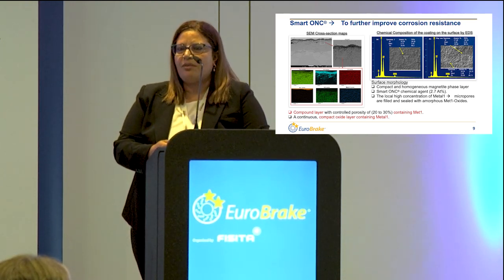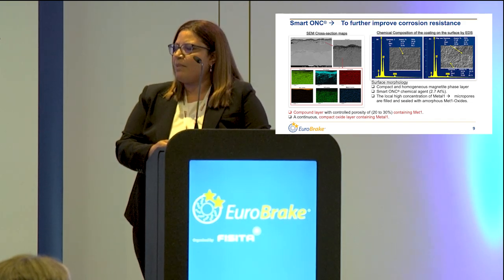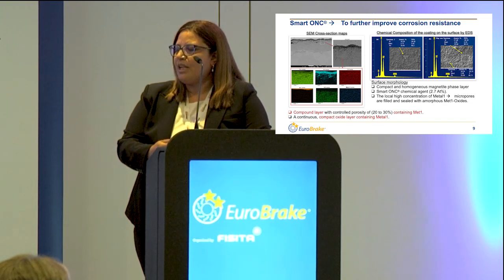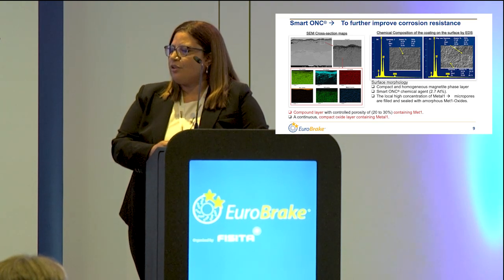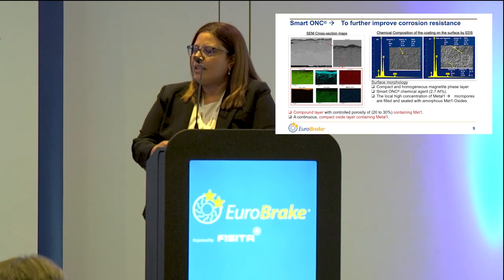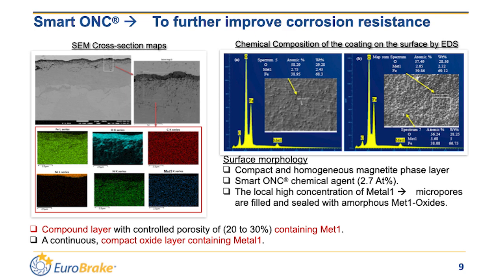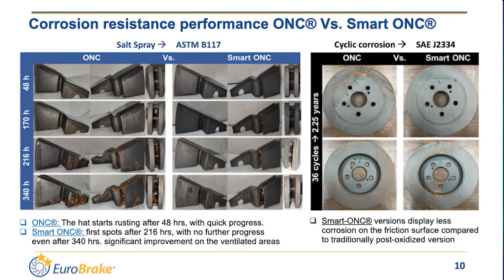With the chemical composition done by energy dispersive spectroscopy, we can see that we have a compact and homogeneous magnetite phase, which contains 2.7% atomic of Smart ONC chemical agents. And the local high concentration shown in picture B indicates that the micropores were filled and sealed with the metal 1 oxides. To compare the behavior and the performance of ONC versus Smart ONC, we did additional corrosion testing.